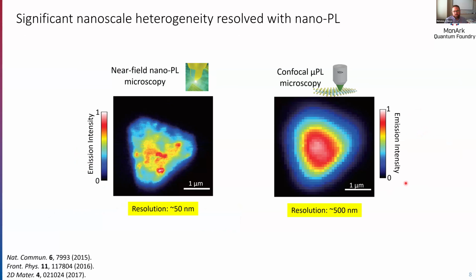But just to give you an idea of what can be achieved with this, here's an image of this two-dimensional crystallite, the light emission taken on a normal confocal micro-photoluminescence setup with a resolution somewhere between 1 micron and 500 nanometers. And here's an image of that same crystallite taken with a nano-optical probe that has a resolution on the order of 50 nanometers. You can see that a really compelling amount of disorder and localized states emerge when you get down into these much smaller spatial resolutions.